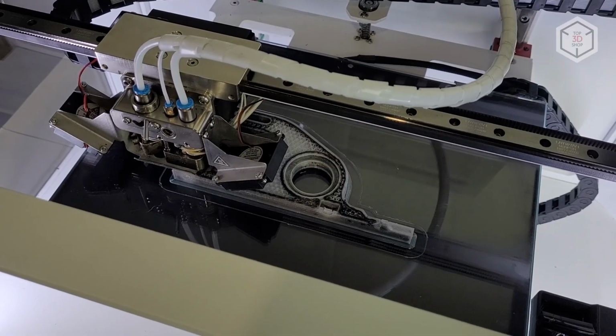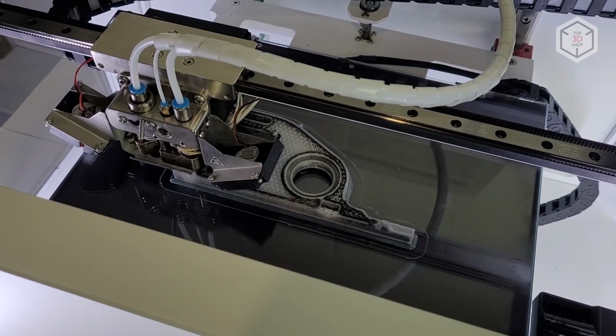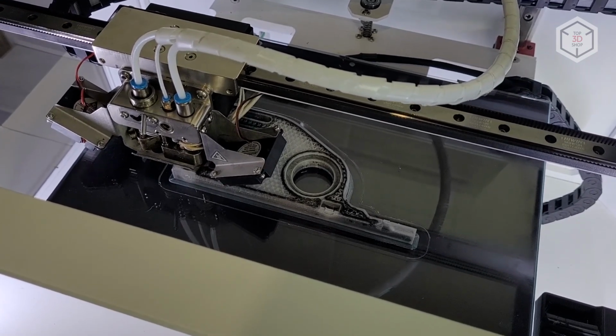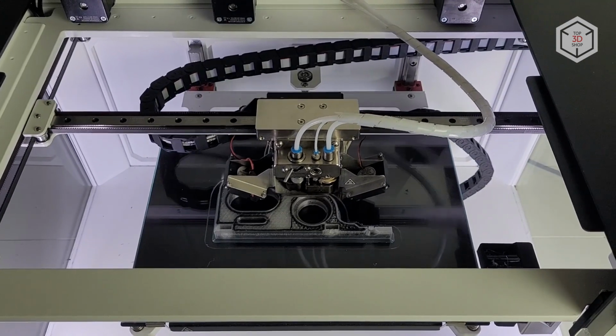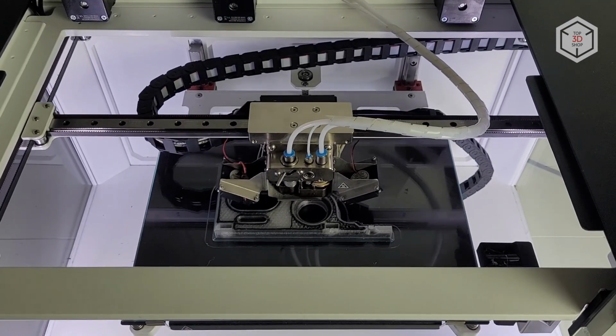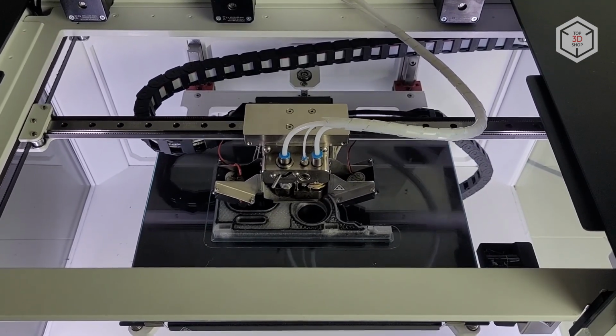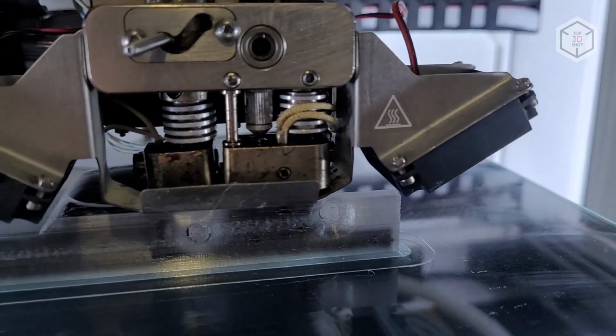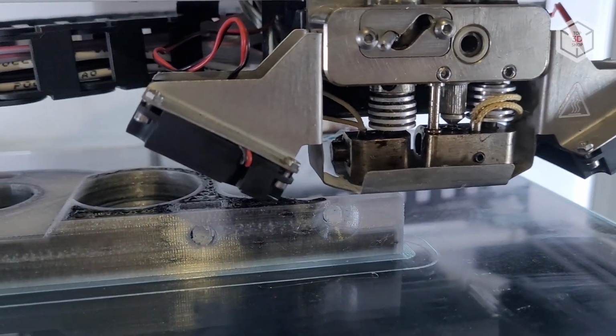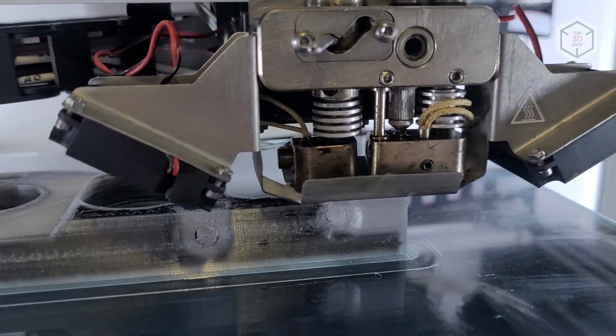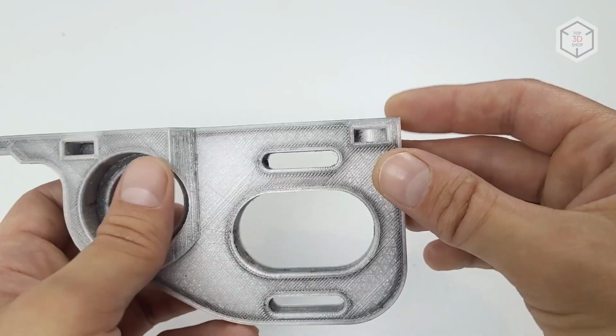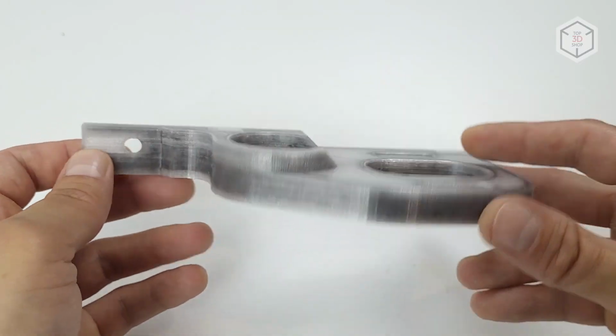For our third and fourth tests, we tried printing parts not designed for this printer. The suspension element of the radio-controlled car turned out right only with reinforced contours. The fiber infill was almost nowhere to be found, and even a couple of areas that could be good to reinforce came out purely plastic because of the specifics of the model. In other respects, the part was printed well, being definitely stronger than the non-reinforced part would have been.